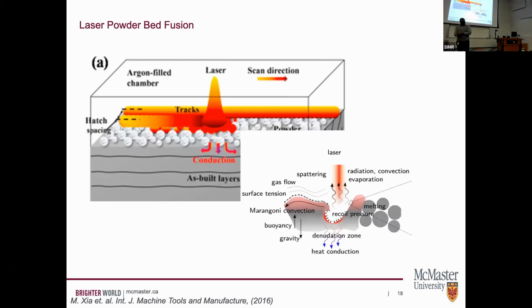This particular manufacturing technique is rich with physics that conventionally in other solidification or casting processes, we tend not to contend with. So things like Marangoni convection, not that convection doesn't exist, but at the rate that conventional casting goes, convection is negligible in some of those. You're looking at things like recoil pressure, buoyancy and gravity, gas flow. And so it's physics rich, but I'm going to tell you now and spoil things that I'm not going to be encountering or considering most of these physics, at least at this first pass of what I'm going to talk about. The first pass is, if this is a new manufacturing technique, what sorts of microstructures do they produce and how does it compare with what we already know?